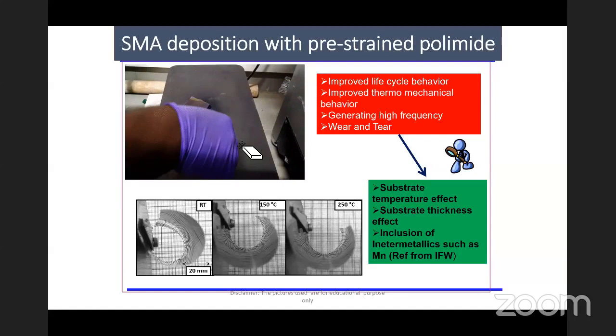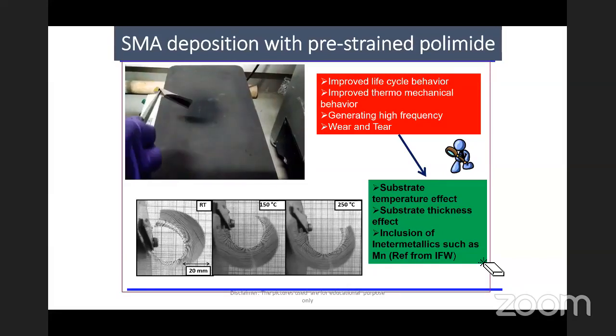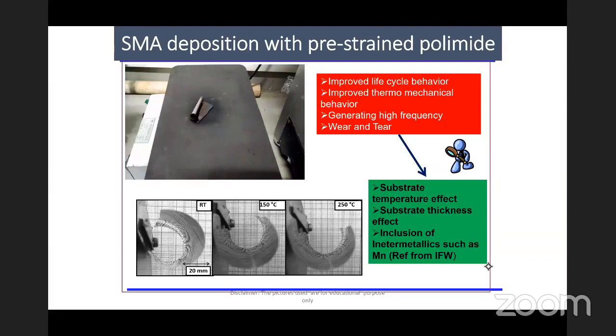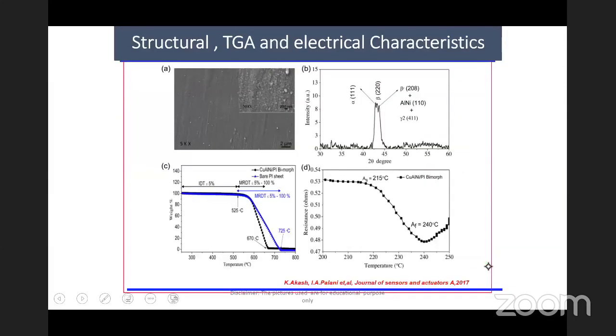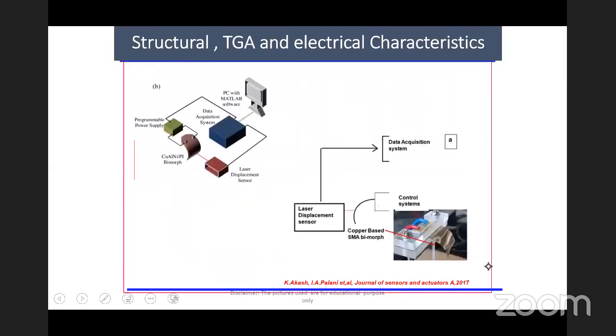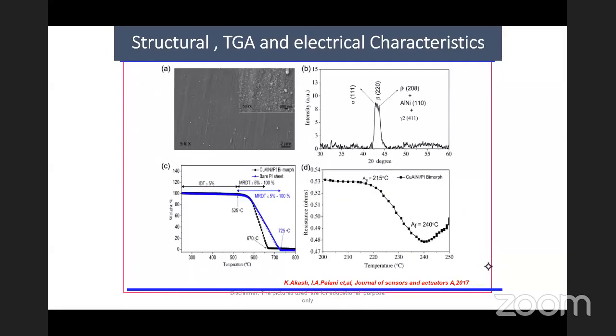Okay, so to investigate the energy applications, we were looking into the substrate effects, the substrate thickness, and then the inclusion of intermetallics to improve its ductility. So this is some of the structural analysis which we have employed. This is a simple SEM micrograph which shows that the samples are plain. We did an XRD analysis to study the particulates which are available, and we also did a small DSC and TG analysis to study the austenite and the martensite behavior of the material.